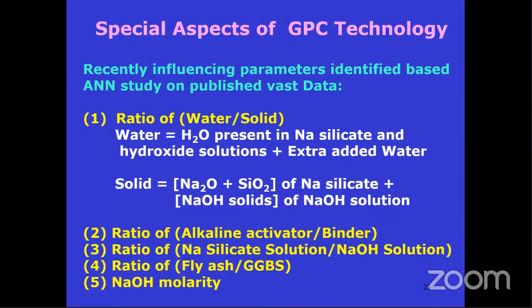So there is no water binder ratio alone. Similarly, there is no one ratio. There are so many factors here. This was done in a paper published in the American Concrete Institute, for which I was a reviewer. Using an artificial neural network, they collected a lot of literature data and proved that. So it is not easy to make a quick design methodology for geopolymer.